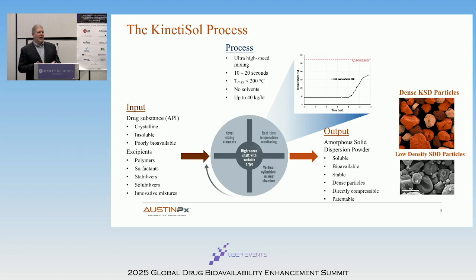You don't have to worry about dissolving your API in a solvent or the excipients. The throughput is pretty good on the commercial scale. It's up to 40 kilograms per hour. You don't have to worry about removing solvents at the end of it. You do add heat to it just based on the friction, but you're usually less than 200 degrees rise, and your material is only in contact for 10 to 20 seconds, so it's quick.